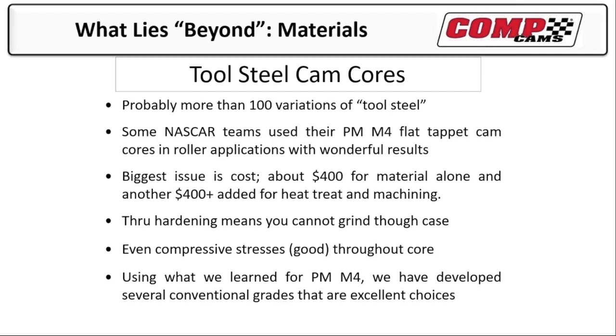The biggest issue with that is the material in a NASCAR cam is $400 for a 24-inch bar, 2.5-inch diameter of PM M4. And then the heat treat is another $400. So basically, you have $800 into material and heat treat alone. Nice thing is through hardening means you can't grind through the case. And because it's through hardened, you have the same compressive stresses throughout the core.